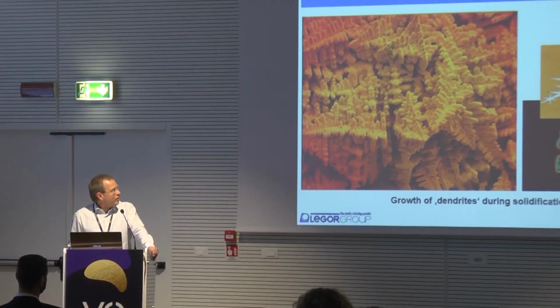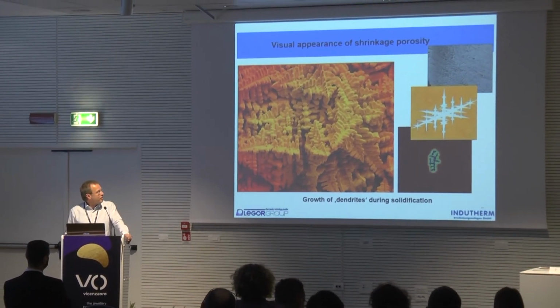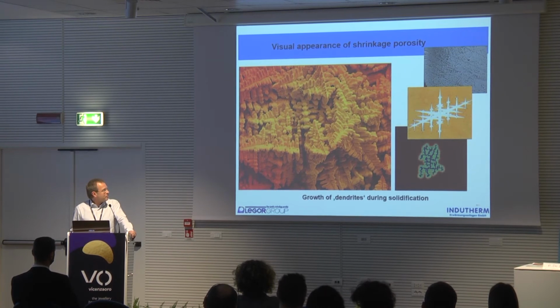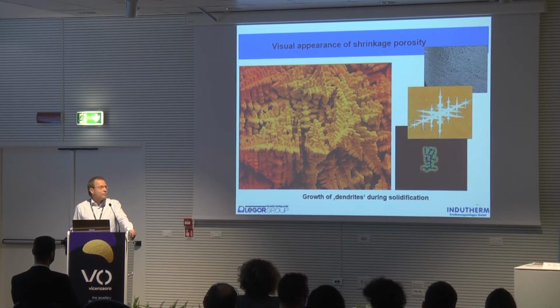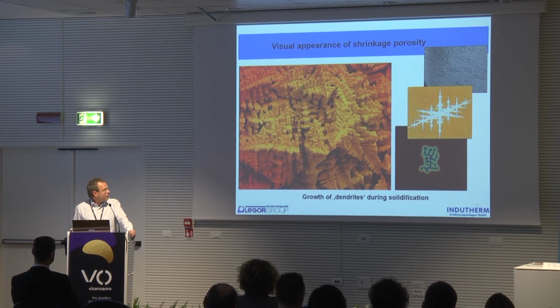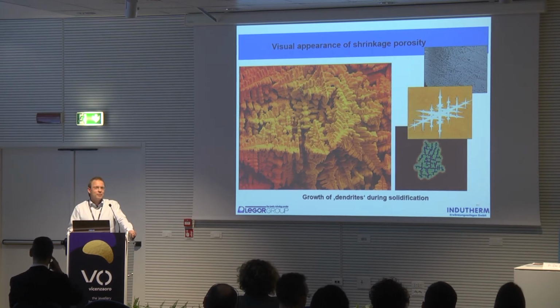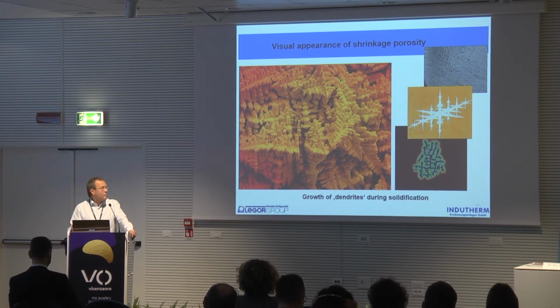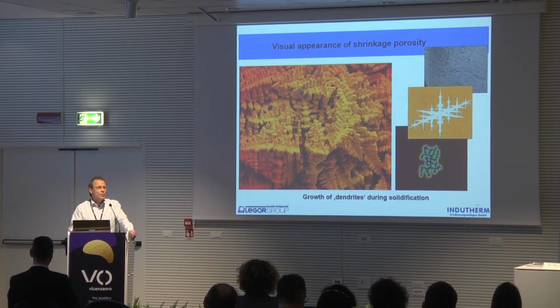In jewelry casting, the porosity will be distributed in a different way, or in any casting process that involves more complex solidification processes. So the irregular shape that we see in shrinkage porosity items is related to the way the crystals grow, like the branches of the tree that you can see here on this photo. And when these branches of the crystals grow, the metal shrinks in volume and you will have voids. And if metal can feed these voids, then porosity can be avoided.